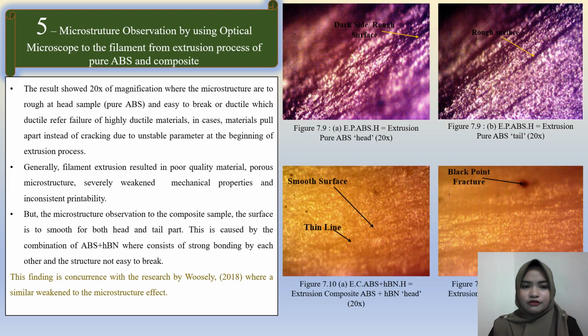Then for number 5, microstructure observation using an optical microscope of the filament from the extrusion process of pure ABS and composite. The results show 20 times magnification, where the microstructure is too rough at the head for pure ABS and easy to break, or ductile, where ductile refers to failure of a highly ductile material, in which the material pulls apart instead of breaking, due to the unstable parameters at the beginning of the extrusion process. Generally, filament extrusion resulted in poor quality material, porous microstructure, severely weak mechanical properties, and inconsistent printability.